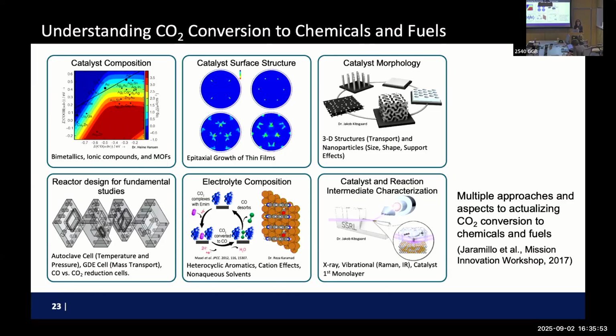Most of the research was in catalysis. Somehow, if CO2 is delivered to the surface of the catalyst, the catalyst can actually make good stuff. So there's catalyst composition, surface, morphology. All these are really important research. In fact, if you're using silver catalyst or other catalysts, they usually make CO. But if you want to make more than C1, C2 plus compounds, bigger carbon-bearing chemicals and materials, you need to go to copper. And copper has to be very spiky.